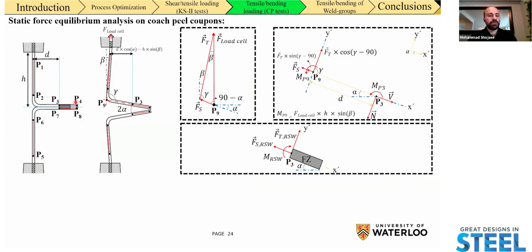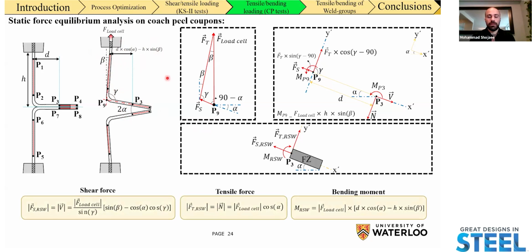We use inspectors, four on each L-shaped coupon, P1 to P4 and P5 to P8. This way, we're able to track all the deformations happening throughout. We can get the evolution of the bending moment arm and of these angles, and as a result, we can get the force components and the bending moment applied to the spot weld, the actual value of it throughout the test. If you look at the equations at the bottom for shear force, tensile force, and bending moment applied to the spot weld, you can see they're all a function of geometry, which is these trigonometry functions at the bottom here.